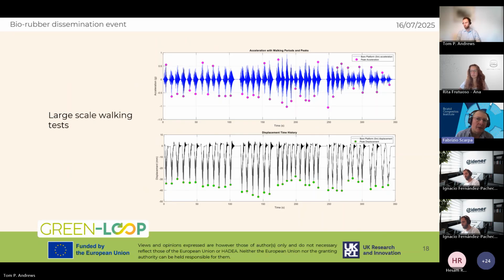Some more interesting results have been measured when we consider large-scale walking tests. So these are the typical spectra of a large-scale test. We measure the peak acceleration and also the displacement time history from the sensor on the platforms. And we calculate the root mean square average and standard deviation so we can compare the different configurations. Next, please.